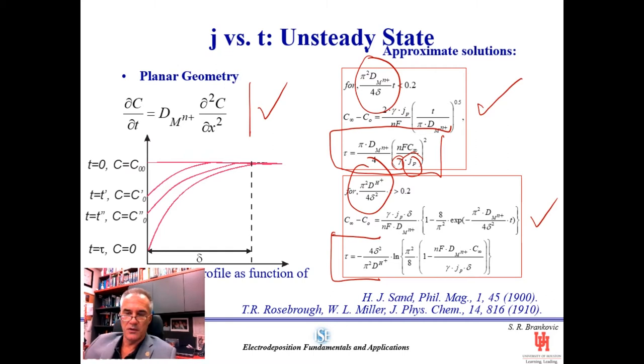Also, your off time, which is typically current zero, or your equipment has an off time disconnected, in general has to be long enough to allow recovery of the concentrations at the interface. And in general, the rule is that your off time should be about 3 to 4 times longer than your pulse time. This comes from the math. I'm not going to present this, but more of this you can see in different pulse current deposition handbooks.